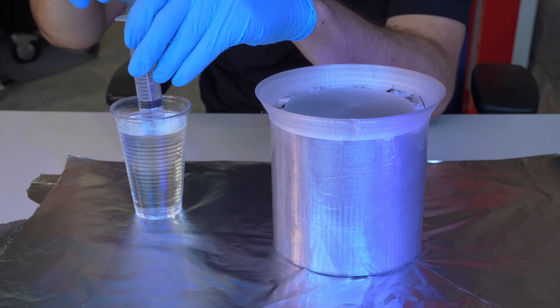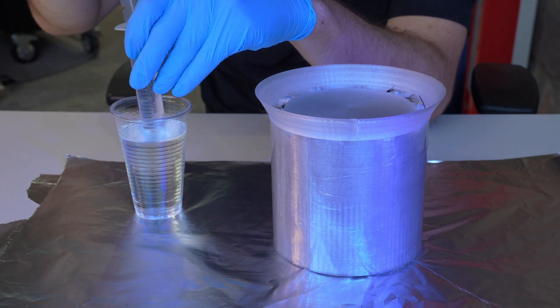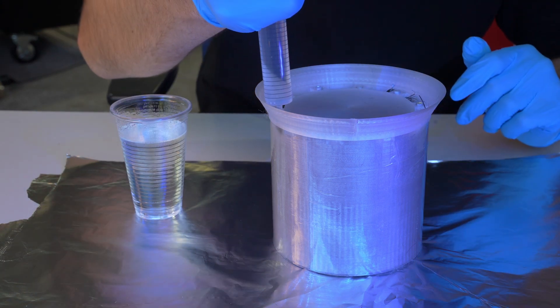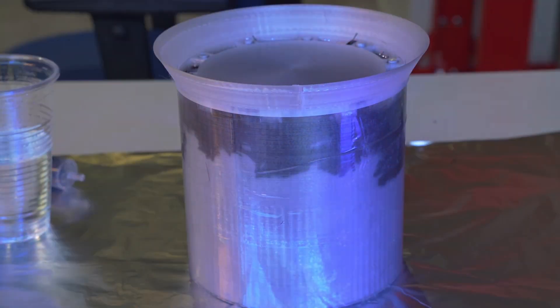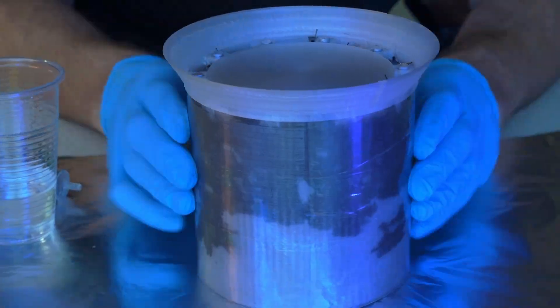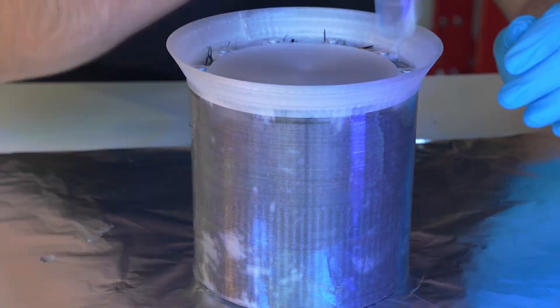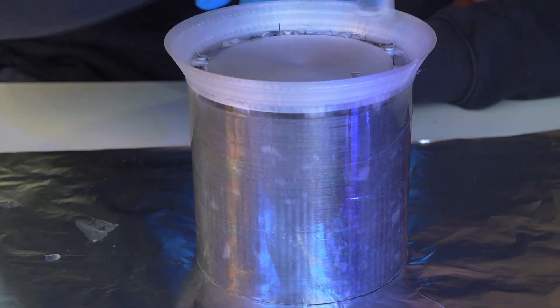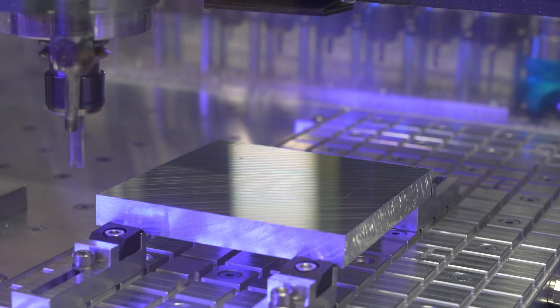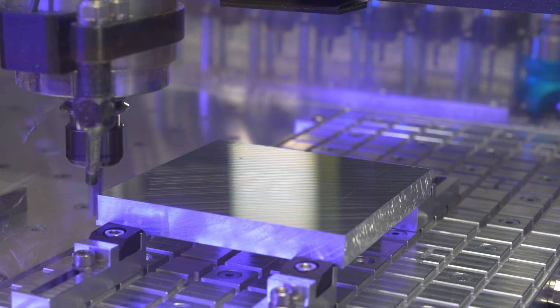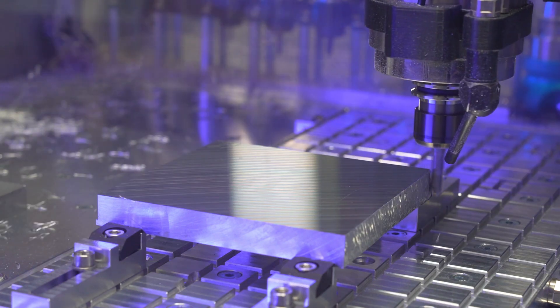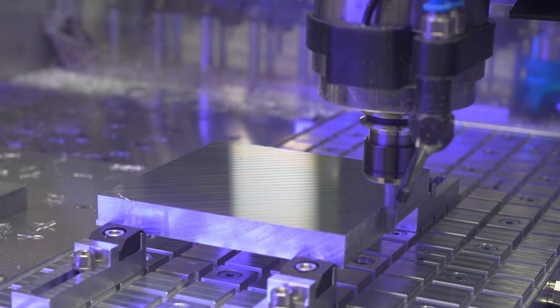We are now using a syringe to pour the epoxy into the funnel and just let it drain by gravity. This can take up to 20 minutes, but in our experience, the resin will even flow six hours after this because it has such a low viscosity. Now we will mill a fixture to clamp this part into the CNC machine to mill it precise.